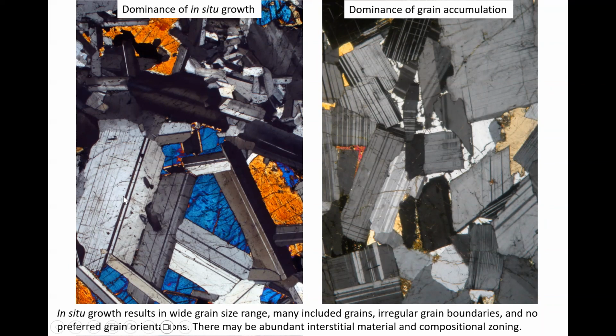And you've got no fabrics, a lot of compositional zonation, and a very wide range of grain sizes, because if nucleation is going on continuously, the little grains are the ones that have only just nucleated, or there was a higher nucleation density before they met their neighbours. Whereas here we've got current sorting, so the grain size variation tends to be much smaller. And what else have I got? Irregular grain boundaries, no preferred orientations, etcetera.